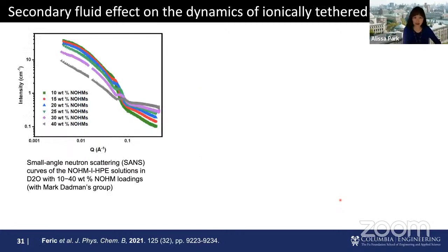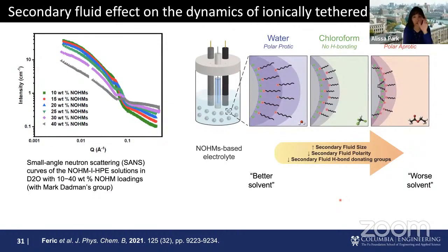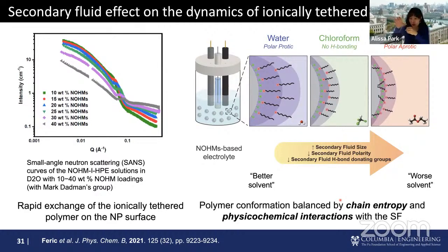And we also did the SANS data, small angle neutron scattering, with our colleague Mark Dadman, and we found out that this tethered polymer system is a little more complex than we thought. Initially, in all our known systems, we thought that all the polymers were tethered onto the surface. But whenever we calculated grafting density, it was higher than we thought. What we found out is that in between tethered polymers, there is a polymer stuck in between. Those polymers don't get detached from that region, but they can swell or take a different conformation depending on the secondary fluid, so we started calling these interacting polymers.